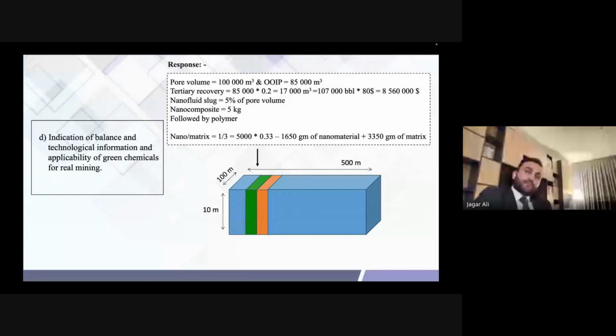So for your first question about aggregation, yes, I was just answering Diman about that. And I showed some pictures of the nanofluids that we prepared over time, for example, for 6 days. When we prepare nanofluid, you will use stirring mixing. But after that, you should do sonication for 2 hours, 6 hours maybe, in order to have good dispersion. And then when you have good dispersion, it will remain for a period of time. So usually we try to prevent the aggregation of the nanoparticles, and we obtain that, to be honest. So it's not a big deal here.